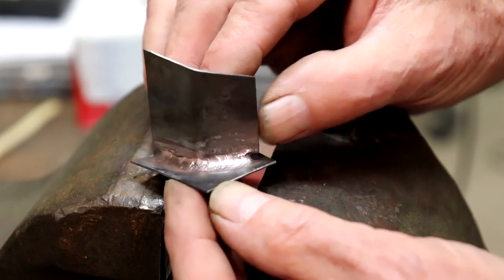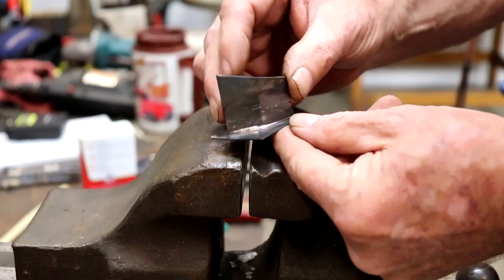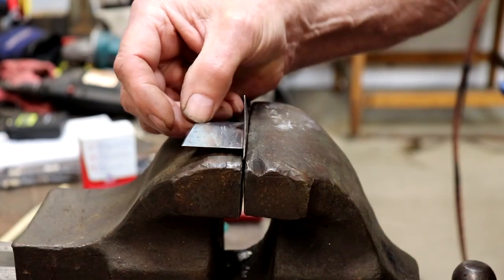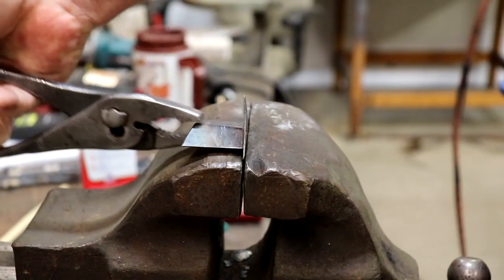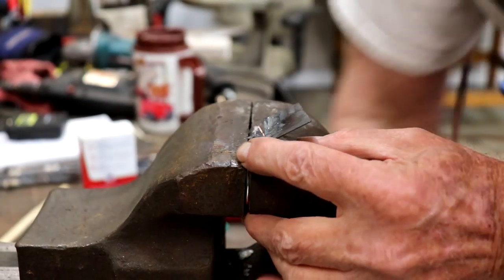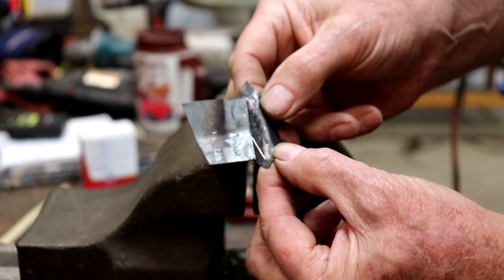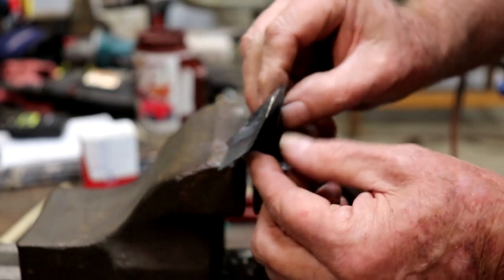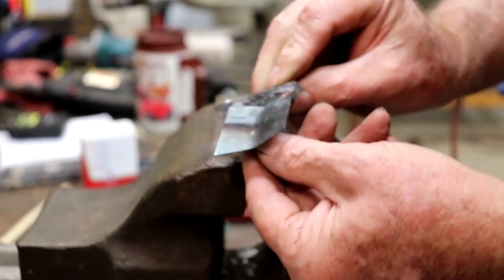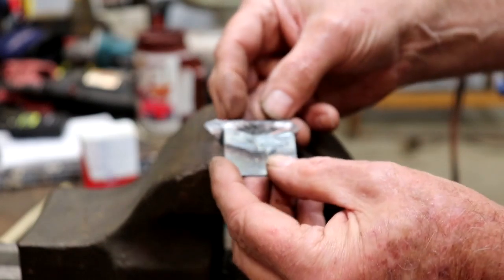Now let's tear them apart and you can see how strong these are. So here's the first one I did with a very small amount of copper. You can see that broke fairly quick, and you can see there how much got underneath it. I went just a little bit past 90 degrees with this piece and it let go. So you can get a nice small fillet in there but it's not going to hold much.